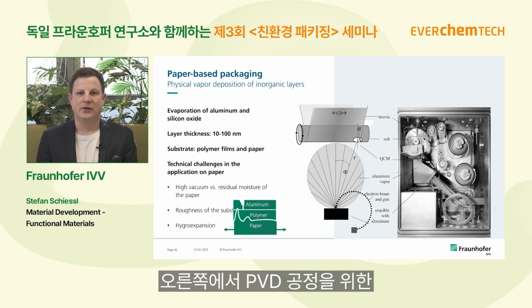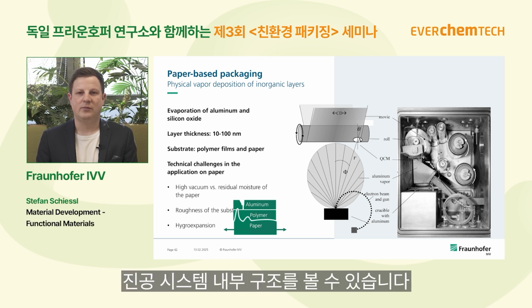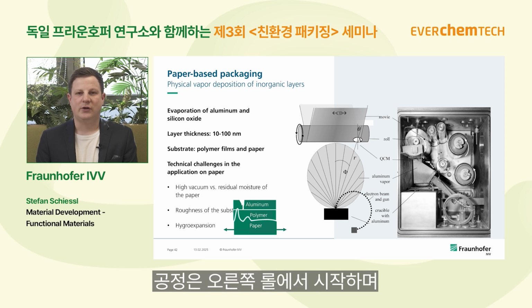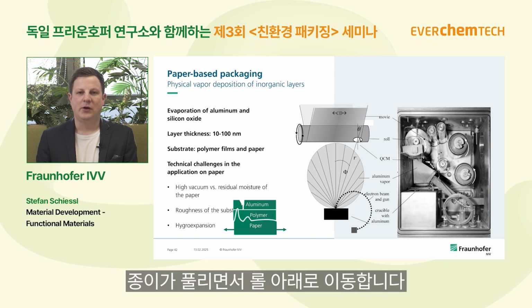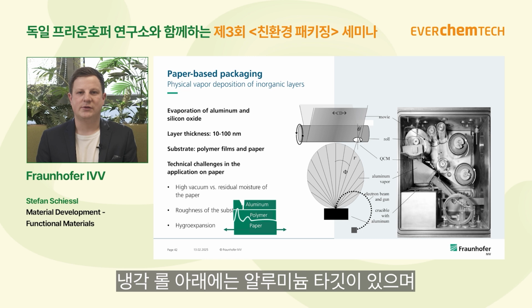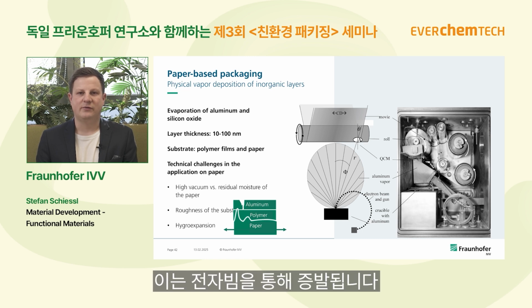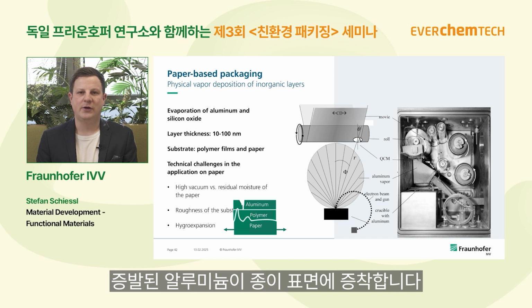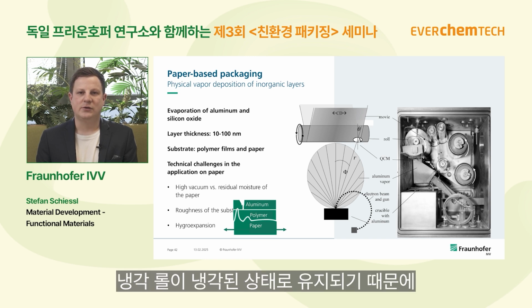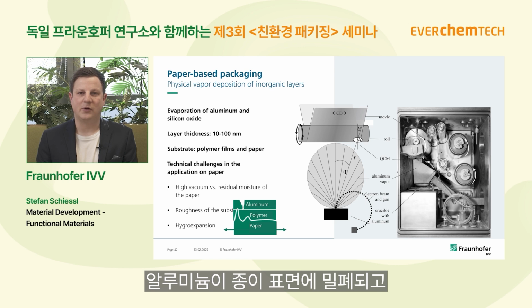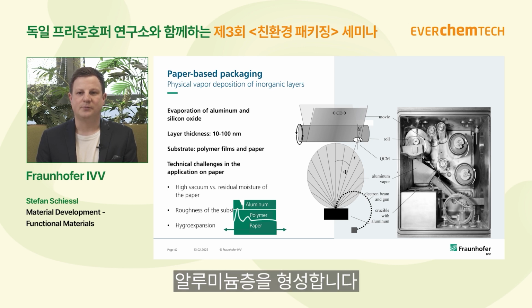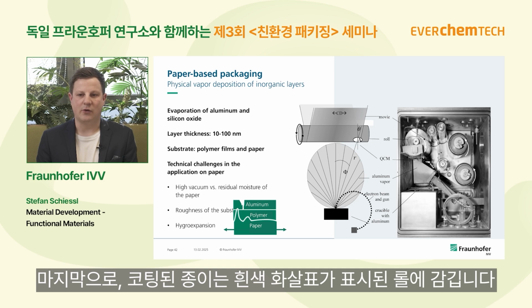On the right hand side you see the interior of the vacuum system that is necessary to apply the PVD process. We start on the right roll, moving the paper below a chill roll. Under the chill roll there is an aluminum target which is evaporated via electron beam. The vapor is condensing on the paper surface, and due to the fact that the chill roll is cooled, the aluminum is building a closed and dense layer of aluminum on the paper surface and is then stored on the last roll indicated with a white arrow.